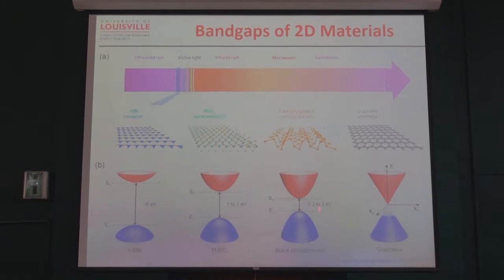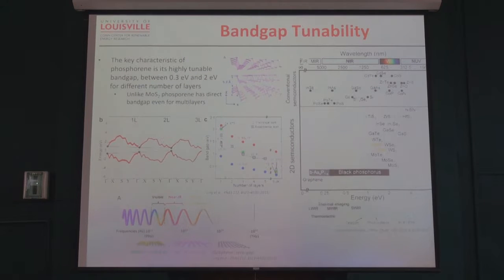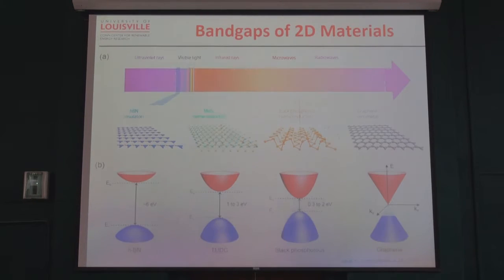Black phosphorus has a band gap of maybe 0.3 eV. But if you go to phosphorene, you can get a band gap of about 2 eV. You can see how big a range you can have in band gap. Typically when we talk about phosphorus, we mean white phosphorus. So this we already talked about.